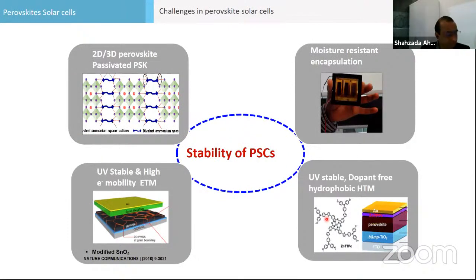Currently, stability is the main issue we are trying to overcome with different strategies, different directions of research we can work on. Most of the earlier used perovskites, which I talked about, have been based on 3-dimensional. So now we know that 3-dimensional perovskite is maybe not an ideal candidate. So people are also working on bilayer type structures, a 2-dimensional and 3-dimensional bilayer, or passivated 3-dimensional perovskite, so the stability can be increased. I think many good papers have been published with more than 1000 hours at 85 degree temperature. You need materials which can encapsulate the device very well.